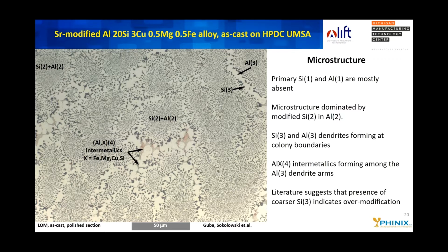So what was done is a strontium modified aluminum 20% silicon 3% copper alloy was cast in that equipment, and this is the resulting microstructure. The interesting thing is that there is no primary silicon massive crystal, and there are no large aluminum dendrites. The microstructure is dominated by strontium modified Si2, secondary silicon, in an aluminum matrix.